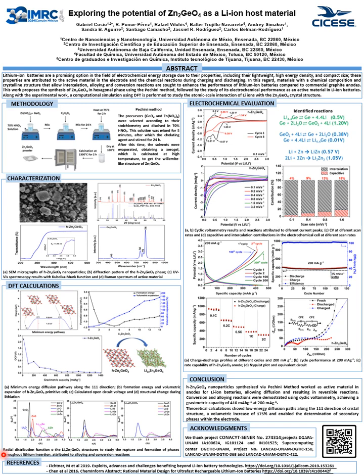The following image displays the radial distribution functions with 6 ions inserted into the structure. A decrease in the intensity of peaks associated with germanium oxide and zinc oxide is observed, along with the emergence of bands attributed to lithium oxide, lithium zinc, and lithium germanium compounds. The final graph illustrates the complete disappearance of peaks related to germanium-oxygen and zinc-oxygen bonds, demonstrating the complete rupture of these bonds, with lithium-oxygen, lithium-zinc, and lithium-germanium bonds prevailing.